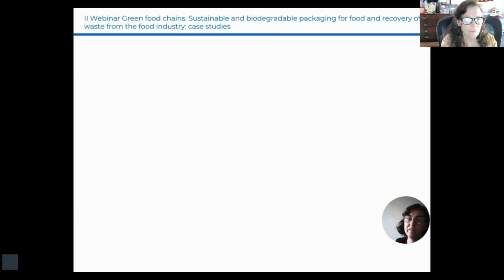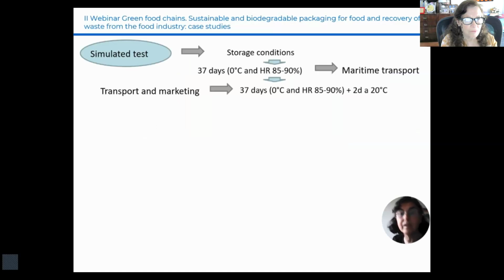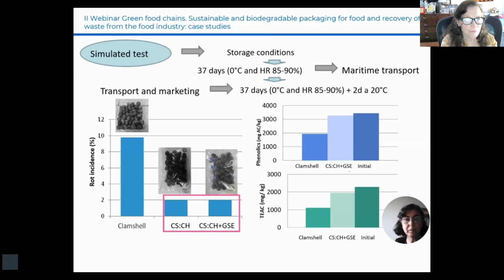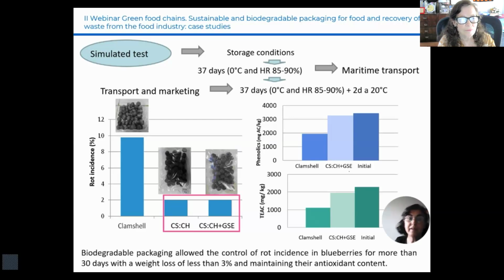A trial was conducted simulating the conditions of maritime transport in containers and subsequent commercialization, also considering thermal abuse. The packaging obtained with the composite and active films reduced the incidence of rot, with a weight loss of less than 3%, thus minimizing economic losses during transport. Furthermore, the fruit maintained its antioxidant capacity and phenolic compound content, which are highly valued in this type of minimally processed products.